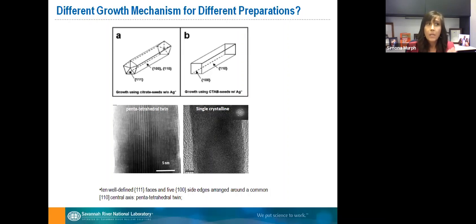So of course, now this tells us that there is a slightly different mechanism influencing the growth of this nanoparticle. And of course, we did a lot of studies, and even now we are not quite clear here if we have the presence of these silver ions, do we have an epitaxial growth of one layer of gold, one of silver?